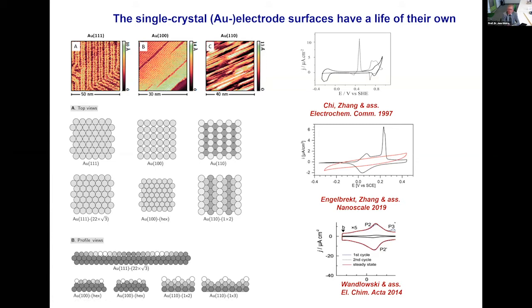But we have to realize that even the single crystal gold electrode has a life of its own, because the surface atoms get unhappy because they don't have neighbors on both sides. They have neighbors on the bottom side, but just air or vacuum on the top side. So they have a tendency of cramming together, and we call this phenomenon reconstruction. They reconstruct. And here you can see there's some sort of reconstruction from the side of the gold 111 surface.